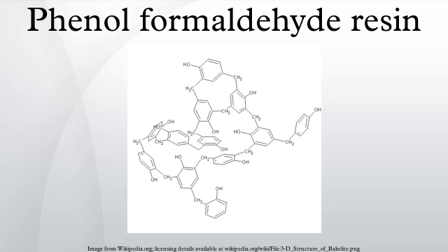The polymerization is brought to completion using acid catalysis such as oxalic acid, hydrochloric acid or sulfonic acids. The phenol units are mainly linked by methylene and or ether groups. Novolacs are commonly used as photoresists. See also photolithography. The molecular weights are in the low thousands, corresponding to about 10 to 20 phenol units. Hexamethylenetetramine, or hexamine, is a hardener added to cross-link novolac. At a temperature greater than 90 degrees Celsius, it forms methylene and dimethylene amino bridges.